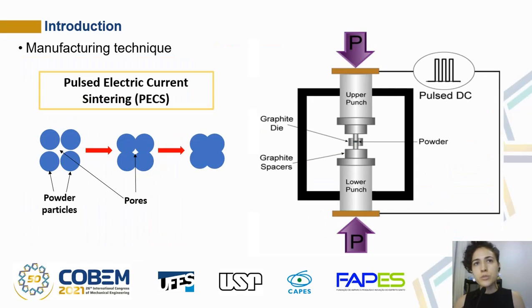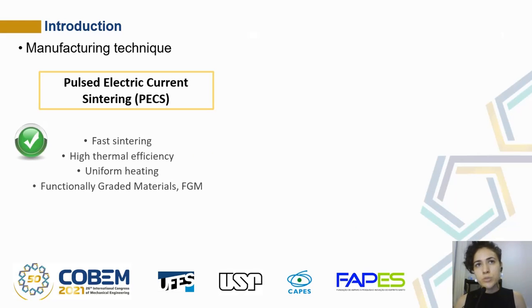The technique used to manufacture the composite was pulsed electric current sintering, known as PECS. This technique combines pulsed electrical energy and mechanical pressure to promote the transformation of a powder housed in the graphite mold into a solid form with the desired composition and density. This technique promotes fast sintering, high thermal efficiency, and uniform heating, and it's usually applied to advanced materials such as functionally graded material.